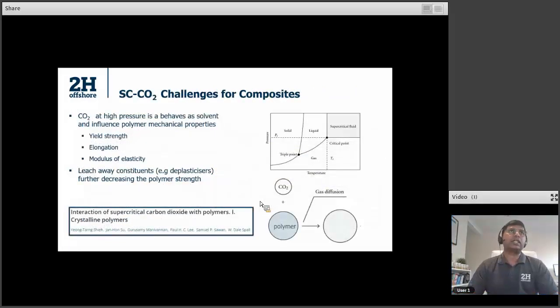But there are also challenges with the presence of SCCO2 for composites itself. There's been numerous literature outside oil and gas where people have studied extensively the presence of and interaction of polymers with supercritical CO2. What the presence of supercritical CO2 does is it influences even the mechanical properties of the polymers. It reduces the yield strength. It accelerates the elongation of the polymer, and it affects the modulus of elasticity.